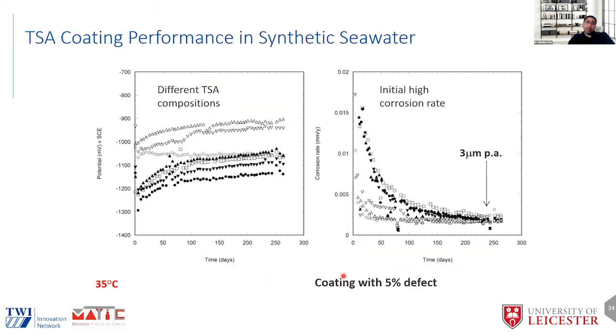So what we saw at 35 degrees, which was another test we did, is again, the corrosion rates are a function of time. We did this test for over a year. After 250 days or so, we found that the corrosion rate got down to a few microns, 3 to 5 microns per year in this case. And in most cases, we are still seeing that TSA is able to polarize steel to well below the so-called protective potential of minus 800 millivolt or so.